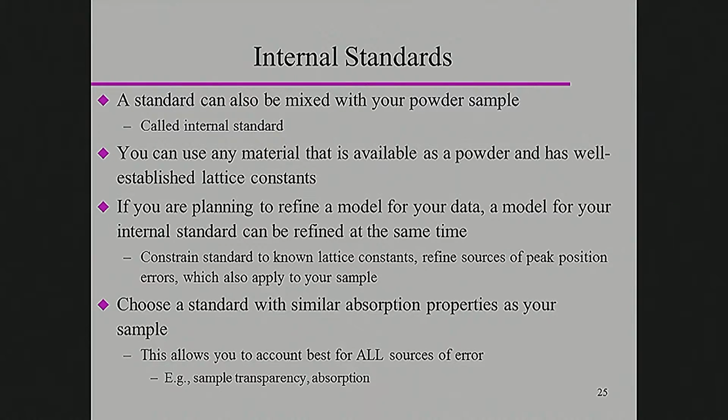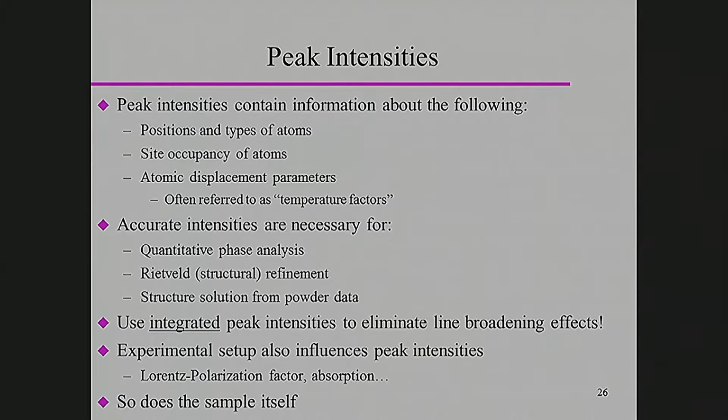If you really have a choice, choose a standard that has similar absorption properties to your sample, because that way any absorption-related errors will be identical for your sample and your standard. Okay? You don't always have that choice, but if you do have a choice, that is really how you should do it. So, that's how we deal with peak positions.